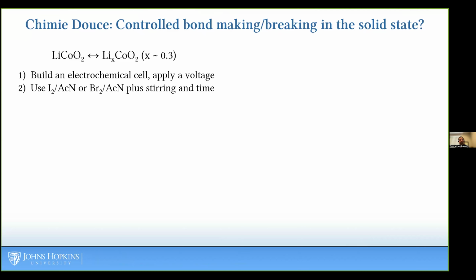Another way to do it is to use a chemical oxidant. So if you start with LiCoO2 and you suspend it either as a crystal or as a powder in a solvent, acetonitrile, with an oxidant like iodine or bromine, and then you wait sufficient time for that oxidant to actually oxidize the lithium cobalt oxide, you can also pull the lithium out, right? You can also go in reverse.